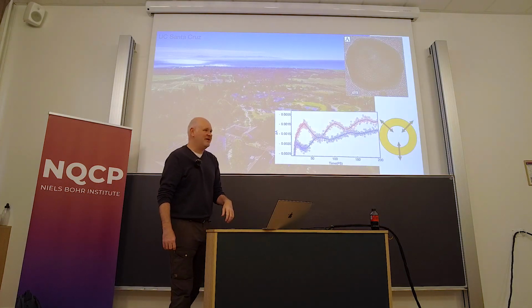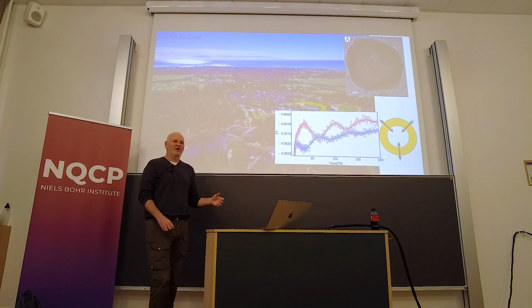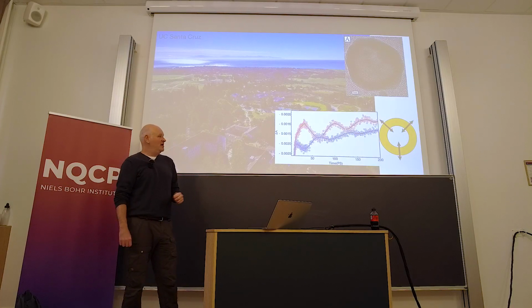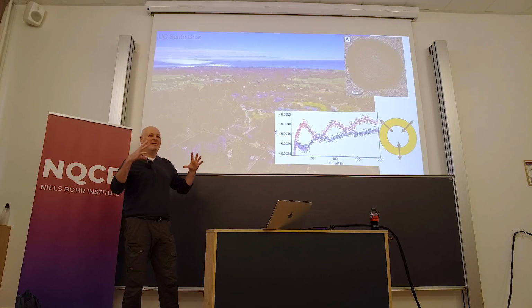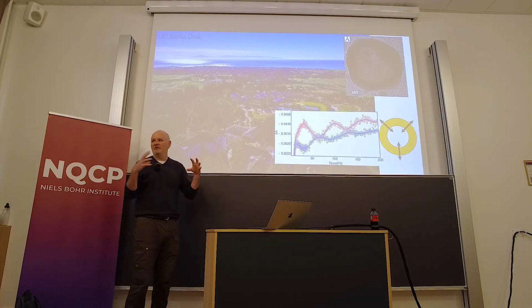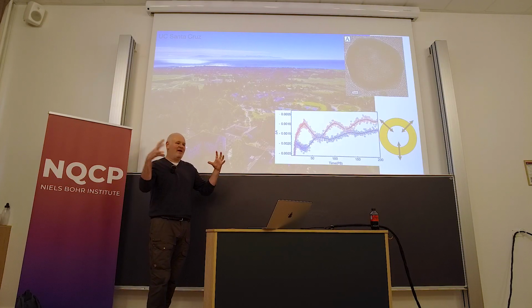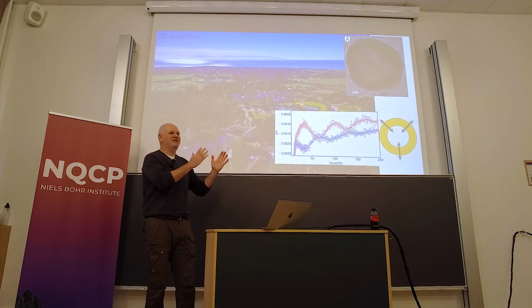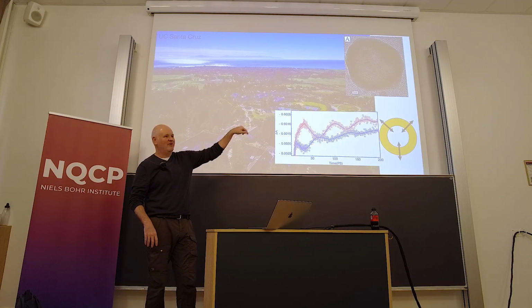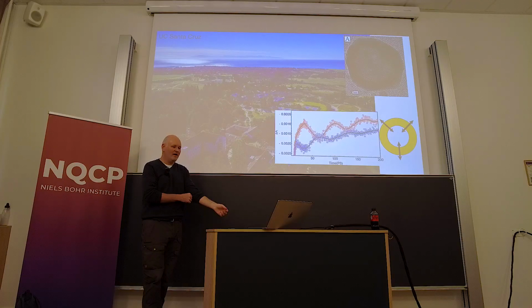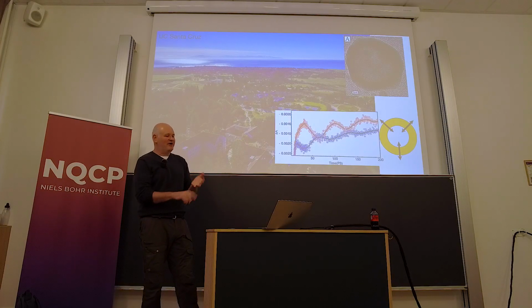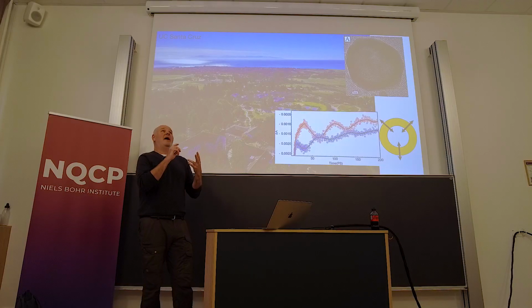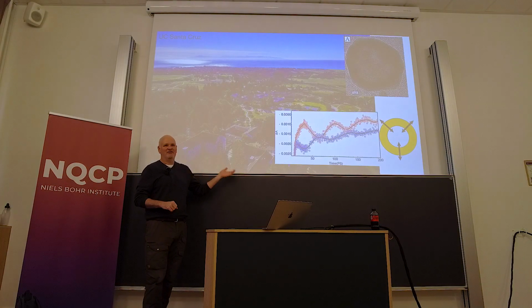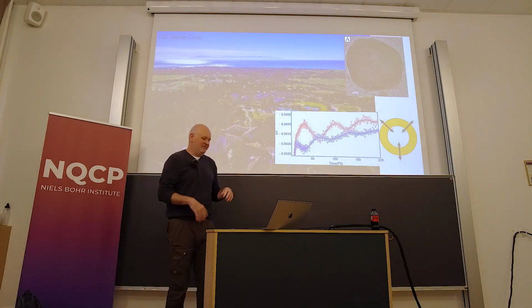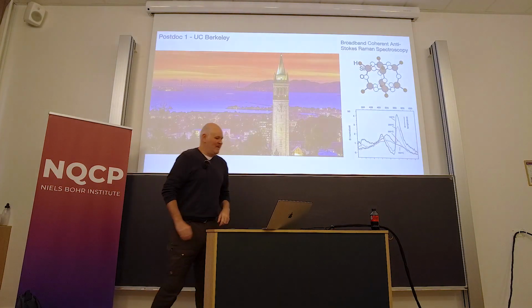They also have very interesting ultrafast properties. So I did a lot of work on ultrafast transient absorption, where you can actually map out the radial breathing modes of these things, because they're literally bubbles of gold. And when you hit them hard enough with the laser, they oscillate. And that actually changes the resonant frequency of them. And so you can map out these coherent oscillations that exist in them. So in addition to nanoparticle synthesis and surface enhanced Raman and transient absorption, I also did biological sensing, because these things are good for biological sensing, and all kinds of crazy stuff. I did too many things.